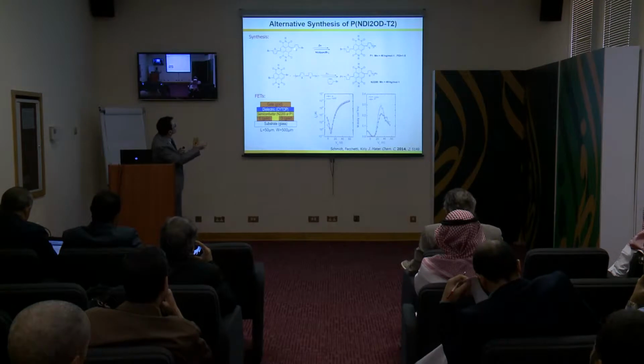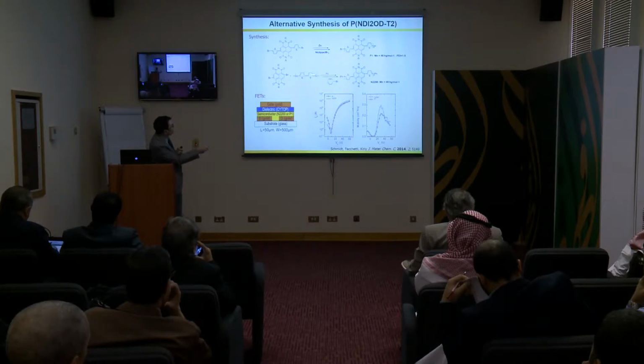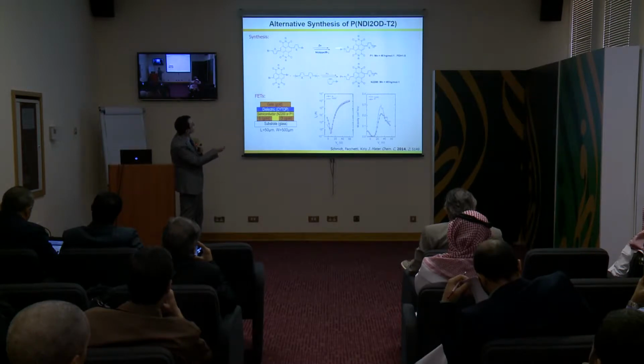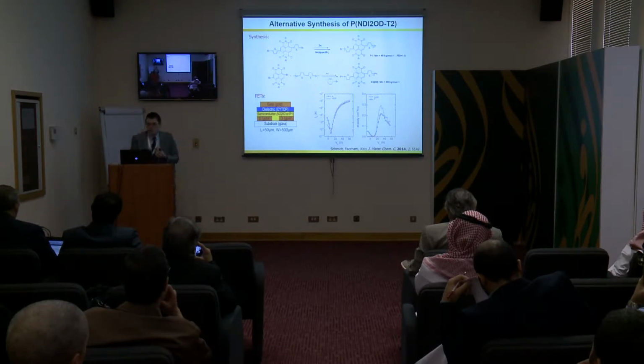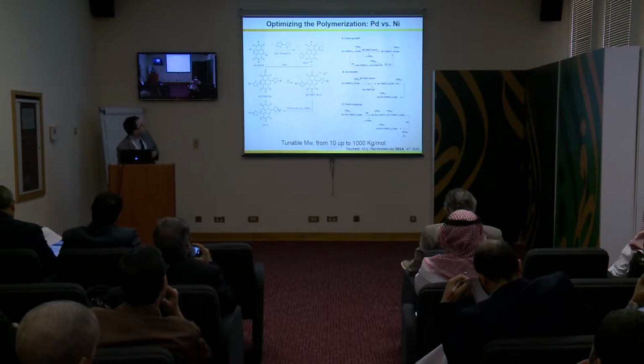functionality here, but starting with a building block and using zinc as a sort of organometallic intermediate to form the polymer, which is the same as the one which we achieve using Stille type of chemistry. And to make the story very short, we can achieve comparable molecular weights and comparable field effect mobility. So this is an alternative route to make this polymer.